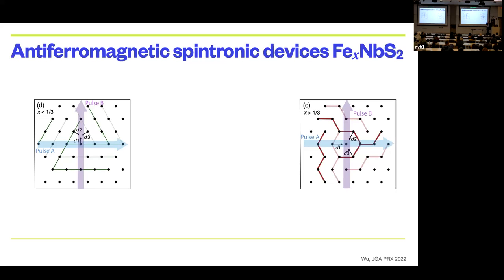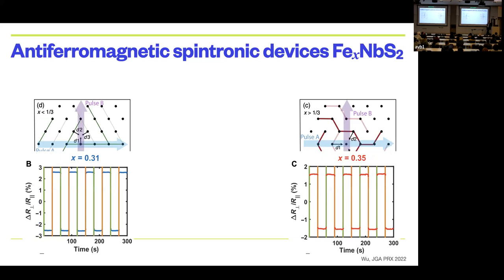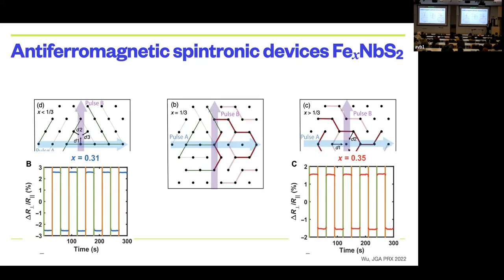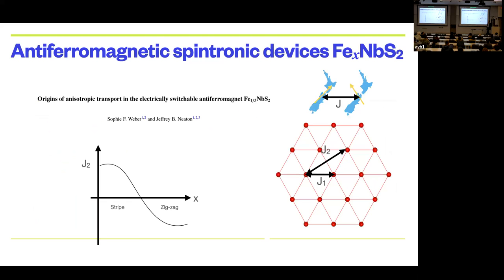But what it showed you is that these iron compounds were right on the boundary of 2 different kinds of order parameters. So it wasn't quite quantum criticality, but it was at least a similar idea that you're basically between energy scales. There's a secondary energy scale, which is the interaction with the next nearest neighbors, and that's basically what's changing as a function of the intercalant in the system. So it seemed to be useful for something.